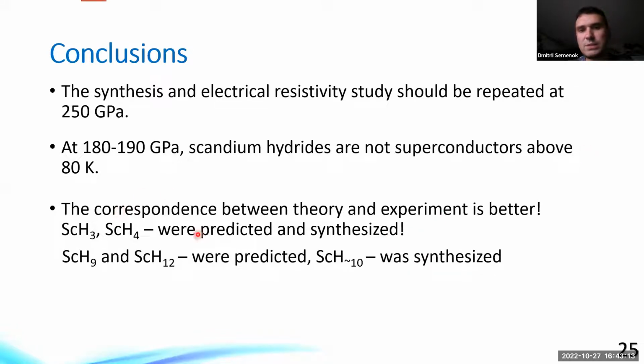Okay, the correspondence between theory and experiment in the case of scandium hydrides is much better than in the case of magnesium hydrides, magnesium polyhydrides. The formation of ScH3 and ScH4 was predicted maybe 7 or even 9 years ago, and they were synthesized. These compounds were synthesized, and their formation was confirmed. ScH9 and ScH12 were also predicted 9 years ago. And finally, recently, we were able to synthesize ScH10.